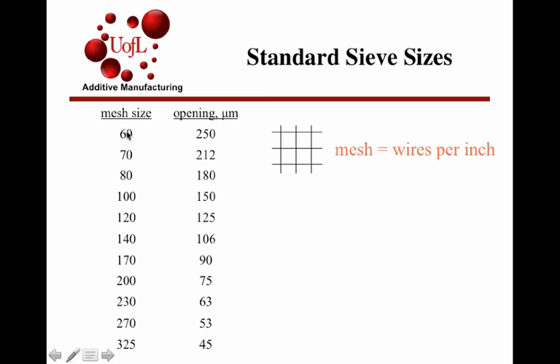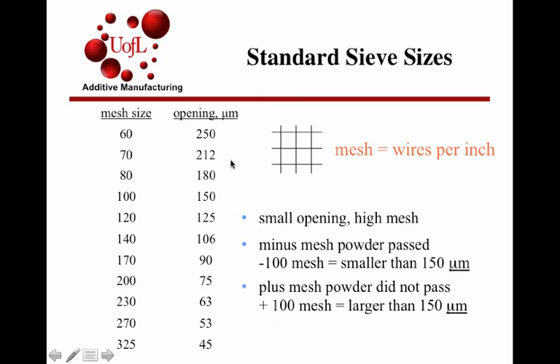Depending upon size of the opening, as the mesh size specification goes up, the opening size goes down. The mesh size is measured by the number of wires present in the sieve per inch. Smaller the mesh size, larger the opening. You will typically have statements such as a minus mesh, such as minus 100 mesh. That means powders smaller than this 100 mesh, which is 150 micron opening, will be able to go through that mesh. So all particles below 150 microns can be represented by the term minus 100 mesh. Consequently, a plus 100 mesh means all particles larger than 150 microns, collected based on what is retained inside that sieve.